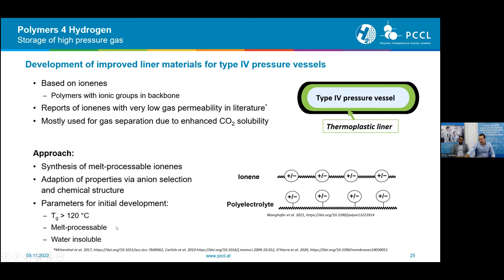Then, very important, of course, is also that the material is melt processable, as I already said. Otherwise, we cannot manufacture those liner materials, those liners. And the material also needs to be water insoluble because the leakage testing of those pressure vessels is usually done with water. If the liner then dissolves, it would be rather bad.